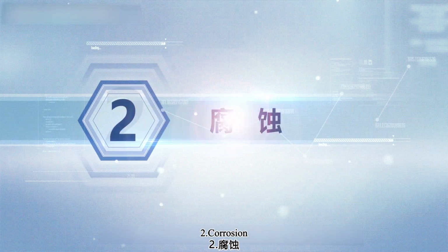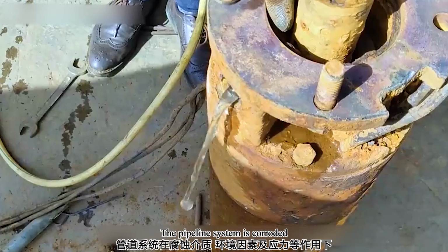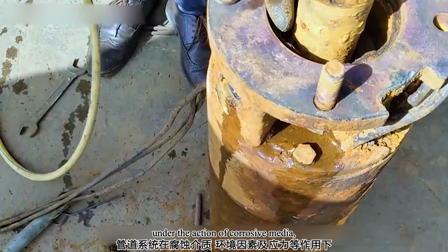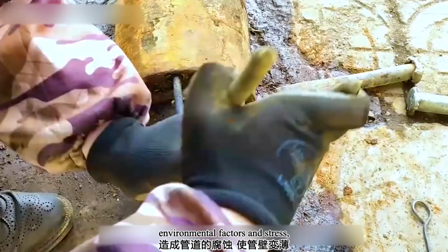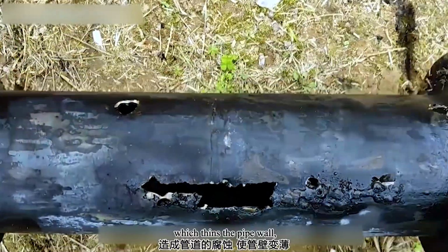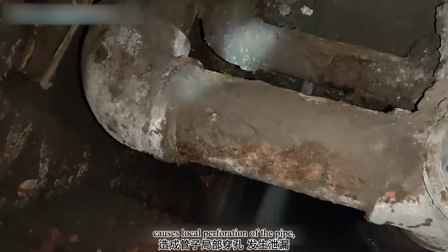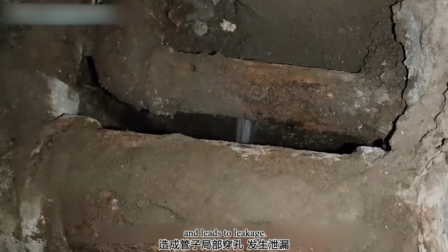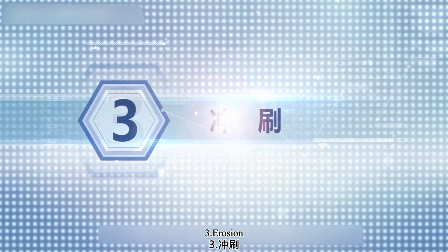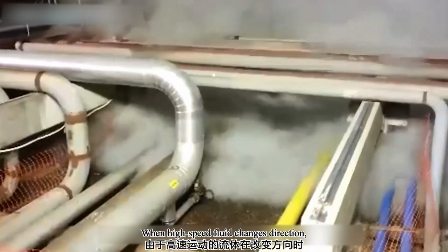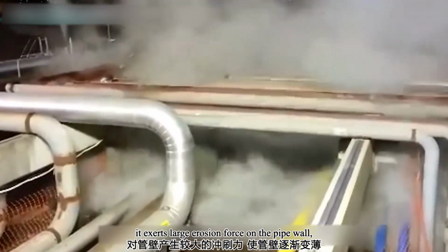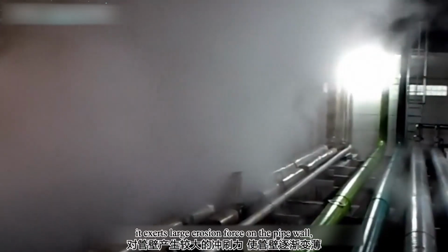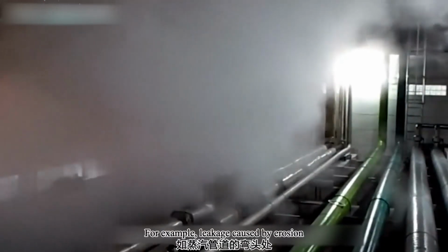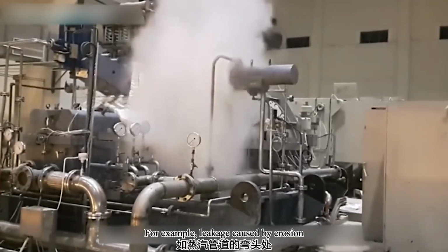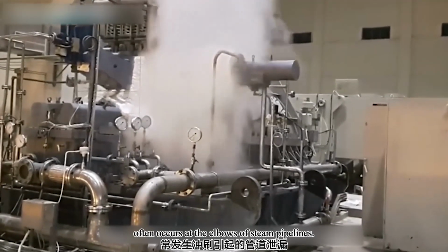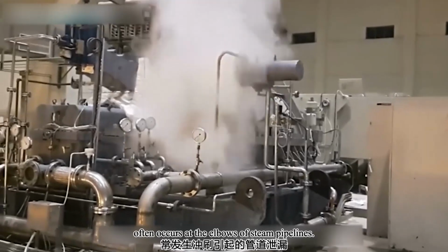Second, corrosion. The pipeline system is corroded under the action of corrosive media, environmental factors and stress, which thins the pipe wall, causes local perforation of the pipe and leads to leakage. Third, erosion. When high-speed fluid changes direction, it exerts large erosion force on the pipe wall, gradually thinning the pipe wall. For example, leakage caused by erosion often occurs at the elbows of steam pipelines.